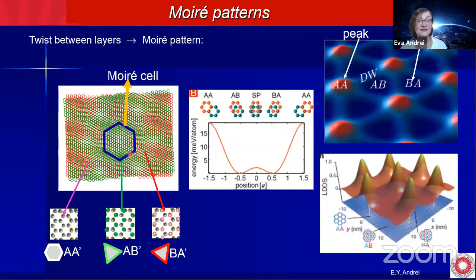But this is not just a pretty pattern. It turns out that energetically, it's much more costly to have an AA region than to have this AB or BA region, which are called Bernal stacking. So if it can, the system will prefer not to have AA regions at all, but of course, this is not possible.